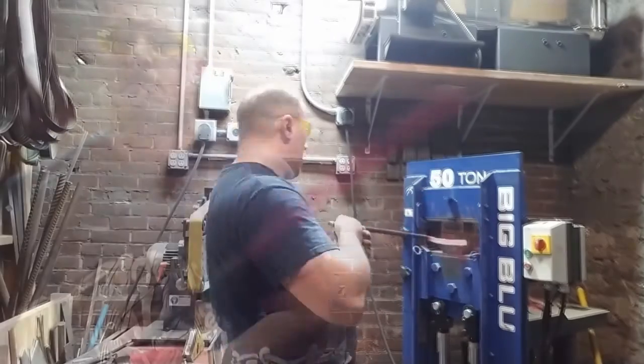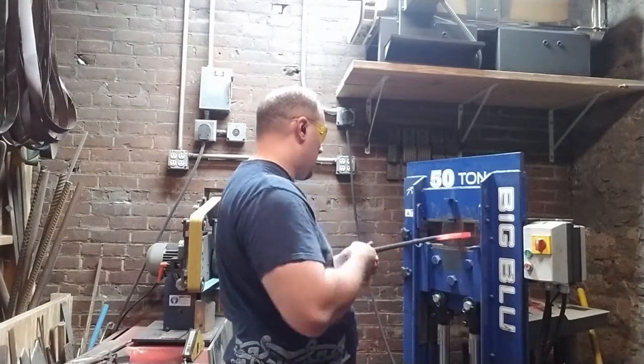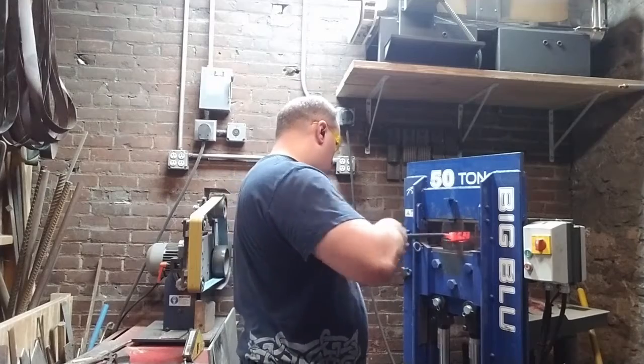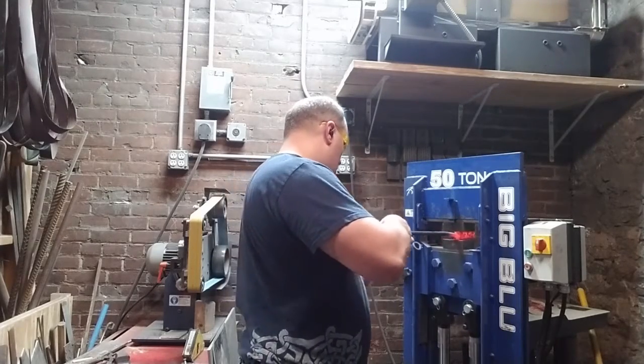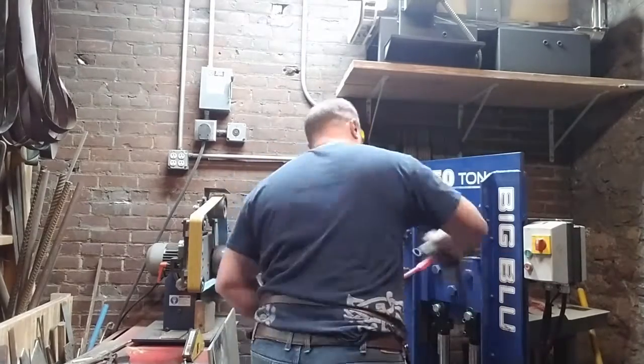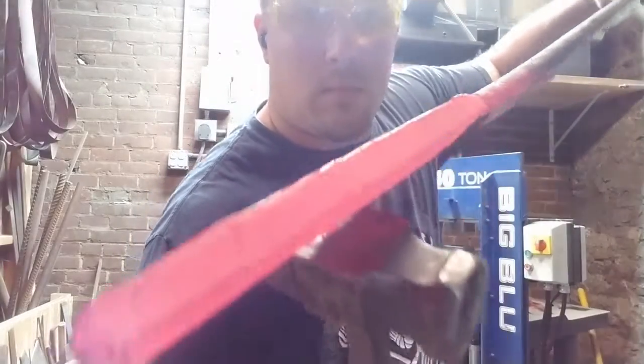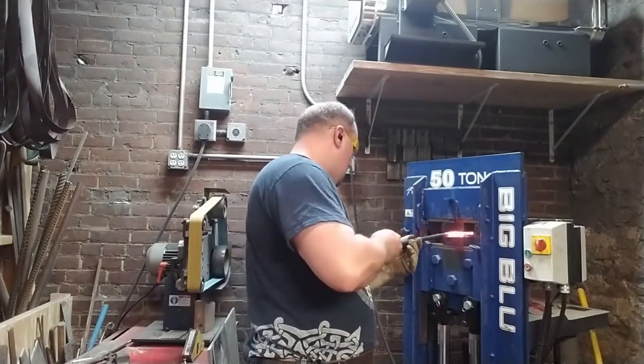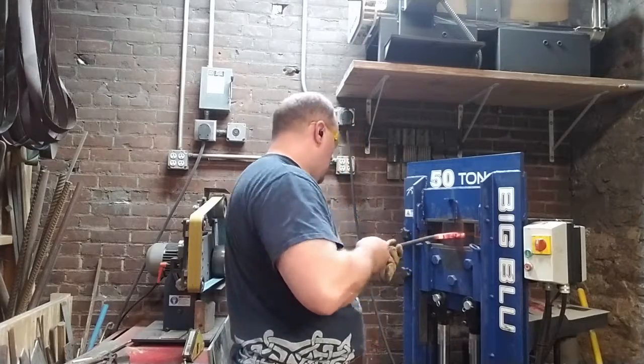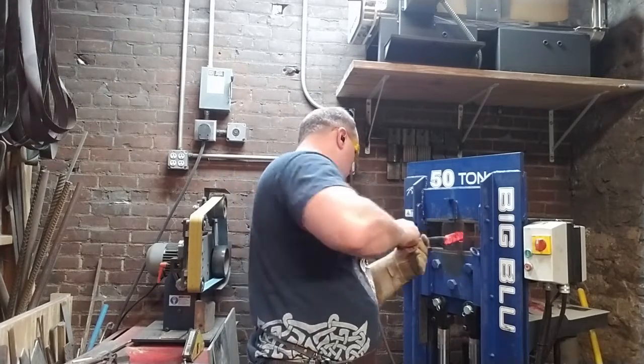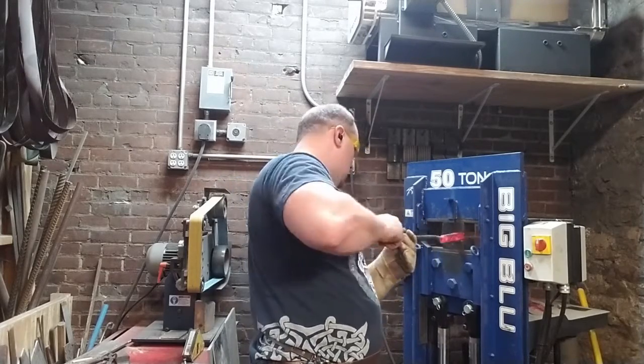I think we got some pretty good movement out of that. But for the next step, we go back to the flattening plates, because we don't want to get our piece too distorted. You can see here I'm starting to forge against the plane of the weld to draw out the length and to make sure that we don't get our billet too wide. Because ultimately what we want is some long square bars so that we can do our twists.